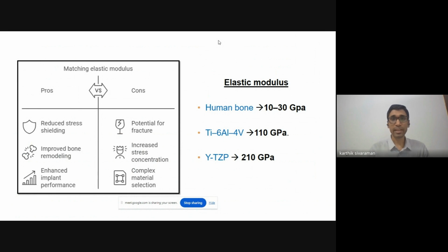So when we talk about the mechanical properties, the modulus of elasticity is very frequently spoken about. So we basically desire an implant material which will have an elastic modulus closer to that of bone, because we want the stresses to be distributed uniformly and less disturbance at the bone implant interface. So when we look at the values for the titanium alloy, which is frequently used, its elastic modulus is 110 gigapascal, which is higher than human bone at 10 to 30 gigapascals. But when you look at the values of zirconia implant, which is yttrium stabilized, it is around 210 gigapascal. So there is a considerable difference.